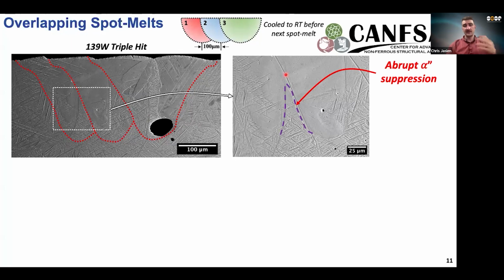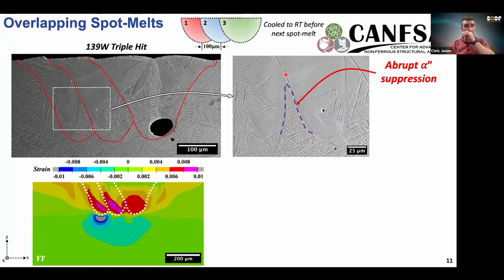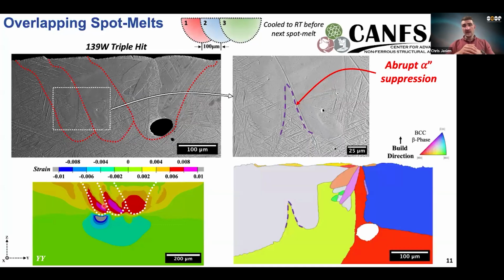So we dove back into our models just to see if they're going to show us something different. And they actually predict something very similar to the previous, where you would expect a more gradual suppression or a gradual reduction in strains. But because that's not what we're seeing, there's got to be something else going on with the material. So as we dive in to see if there's anything going on atomically or microstructurally, we see that this abrupt suppression correlates to this denoted region right here, which is actually a grain boundary, a separation between two grains of material of different orientations.